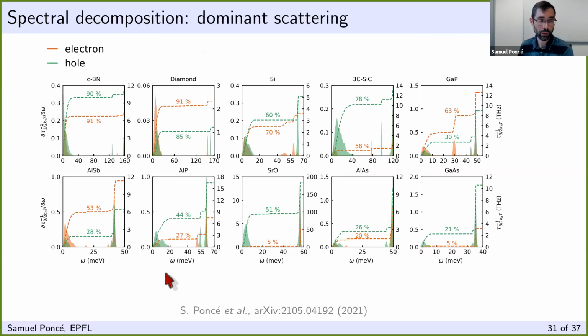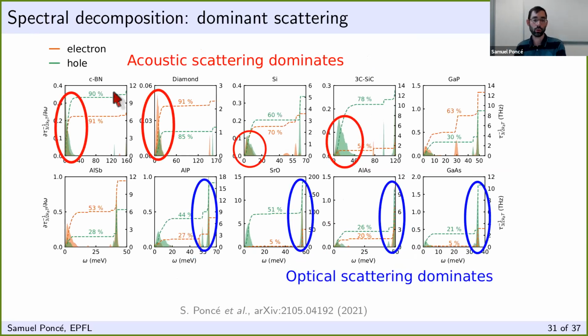Now, what you can also wonder is what the dominant scattering is, and which phonons it comes from. In very stiff materials like diamond and cubic boron nitride, one can compute the spectral decomposition, and one can see that the scattering in those materials is dominated by acoustic scattering, while in more polar materials such as gallium arsenide, it is mostly optical scattering.